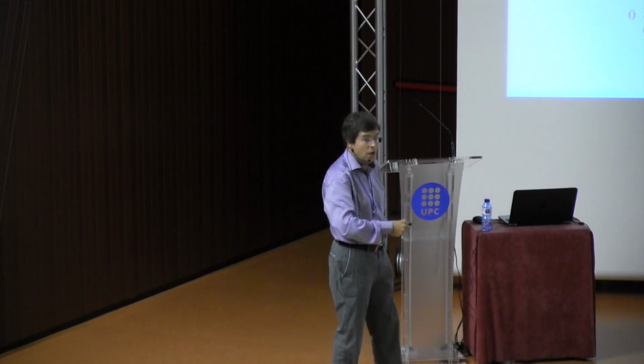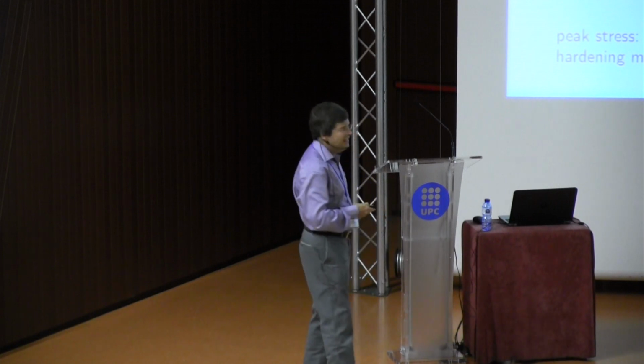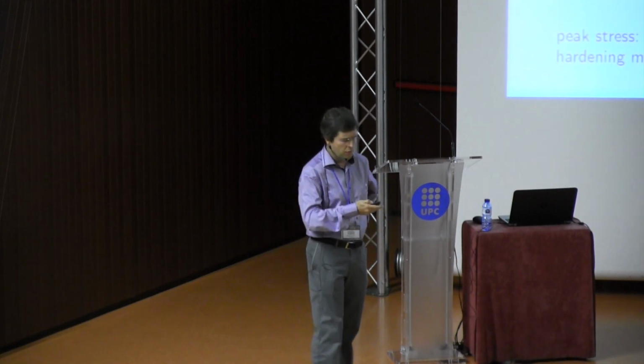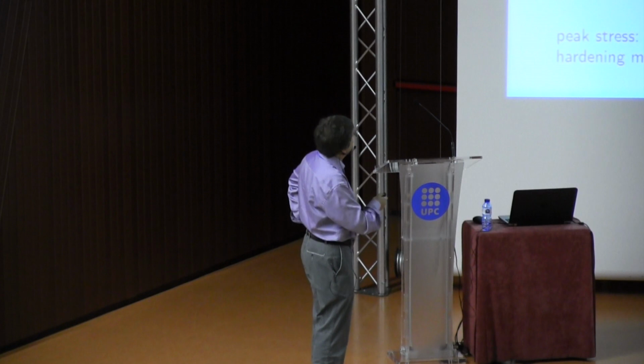In fact, you can see the front here in the computation also, which has a finite thickness, which you can calibrate on the experiment. In fact, this is how we calibrate the intrinsic length. In fact, you can get some analytical solution to check your finite element code especially.